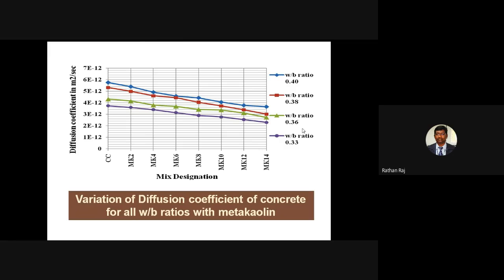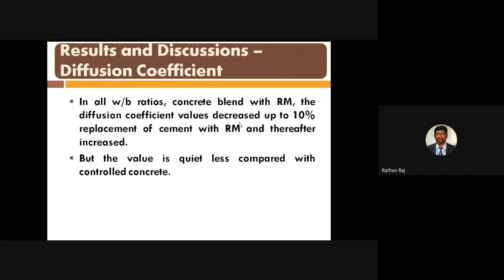And also when we modify the water cement ratio from 0.40 to 0.33, lowering the water cement ratio improves the strength of the concrete. So here the strength is also increasing, and correspondingly the diffusion coefficient is decreasing. So this shows very clearly that the use of supplementary cementitious material will improve the diffusion coefficient. But it is not the case for the red mud addition. So the red mud addition up to 10% shows a decrease in diffusion coefficient.